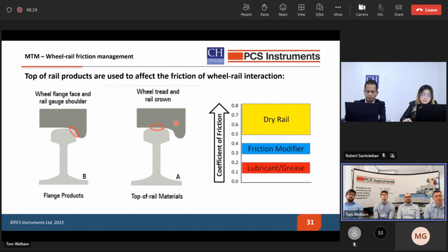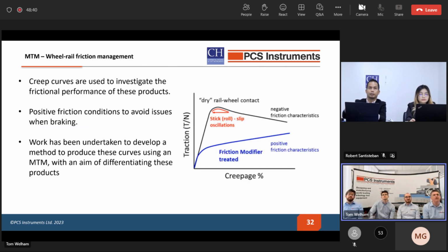With the top of rail product, we're looking at reducing the amount of friction over just the dry contact, but we don't want to just use a grease. We want significantly more friction than that to allow us to accelerate and keep on the track nicely. So the MTM was used as a study in this.